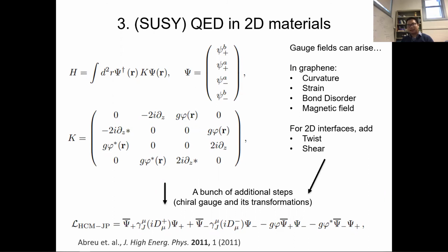In the same sense, when you strain graphene, you get a magnetic field, but you're saying that you can have a quantum Hall current inside, and that's also a wrong statement. You can only have the valley current, because when you go to high enough energy, the two valleys connect to each other and destroy the quantum Hall current. And also the curvature doesn't break time reversal symmetry. It's a non-abelian gauge field that satisfies time reversal symmetry. Yeah, like a magnetic field, but it's not.